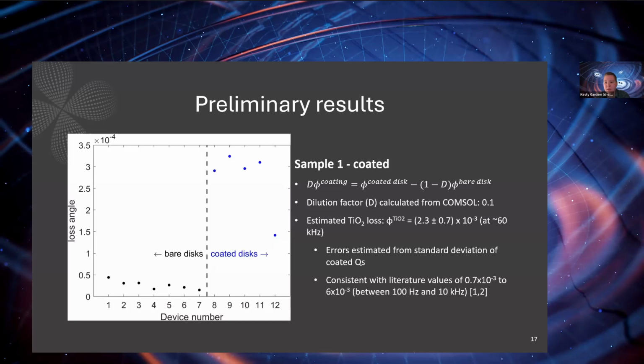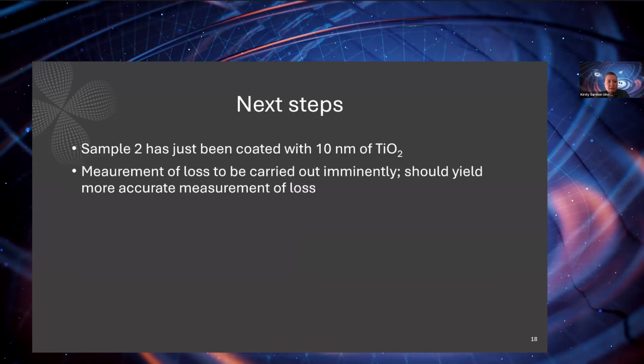Nevertheless, the value that we calculate is consistent with the literature values of 0.7 times 10 to the minus 3 to 6 times 10 to the minus 3. So that's great. This system is working as we would like it to, and it is capable of measuring the mechanical loss. For the next sample, sample 2, which we've just coated with 10 nanometers of titanium dioxide, we have measurements of the bare resonators, and we're going to measure those same resonators after they've been coated. So our error in calculation of the loss is going to be much less, which will be really nice.